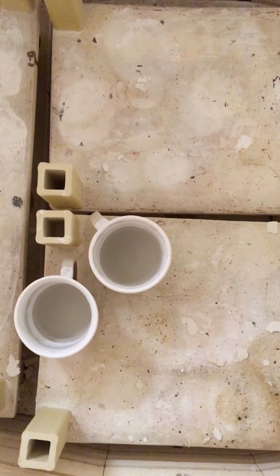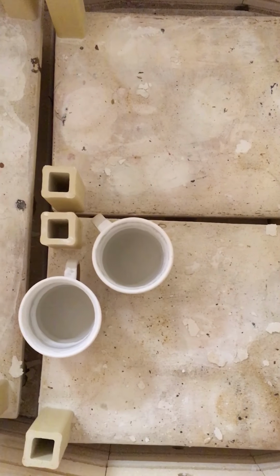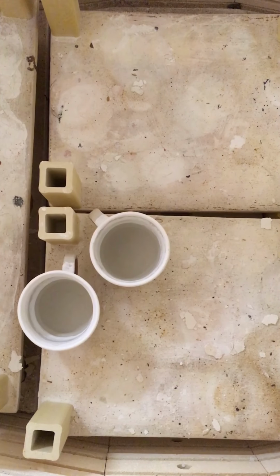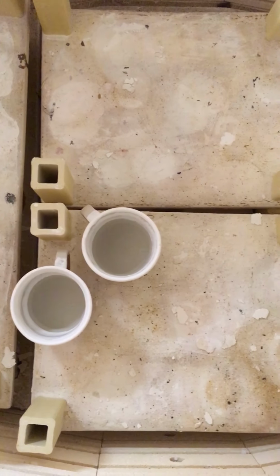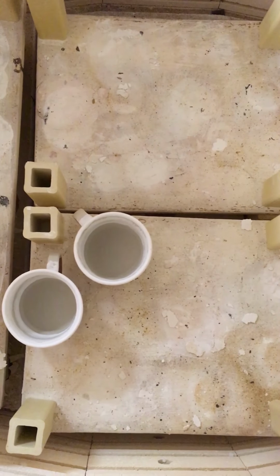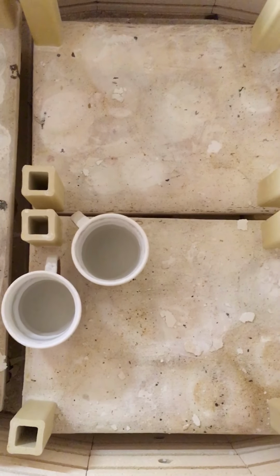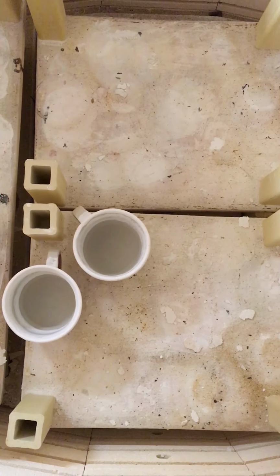As a reminder, when you are loading glazeware, you want to check first and foremost that your shelves are protected. You want to make sure that you're applying kiln wash to the surface on any little bald spots before loading. You also want to make sure that when you're placing the next layer of shelves onto the stilts, that the kiln wash is facing up. Never turn the kiln wash down. We only kiln wash one side of the shelf. That is because we do not want the dry kiln wash to shower down on the forms below.